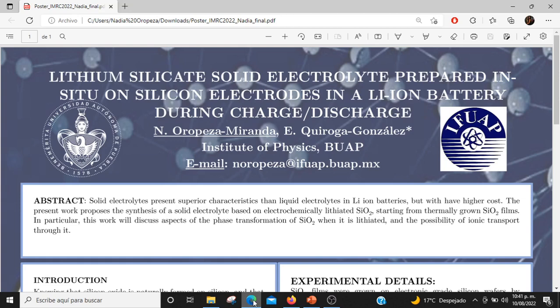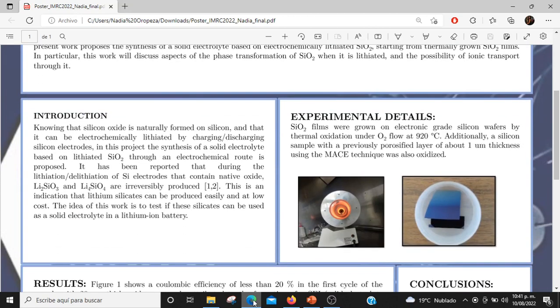In lithium-ion batteries, the electrolyte is one of the vital parts allowing ion exchange. In recent years, there is a trend towards the use of solid electrolytes, but they are expensive. A solid electrolyte option based on abundant elements are lithium silicates, which have ionic conductivity of 10 to the power of -6 to 10 to the power of -9 S/centimeter. They have a crystalline structure that allows transport of lithium ions. And the problem is that despite the fact the electrolyte is based on silicon, which is a very abundant material, it is still very expensive due to the way it is synthesized.